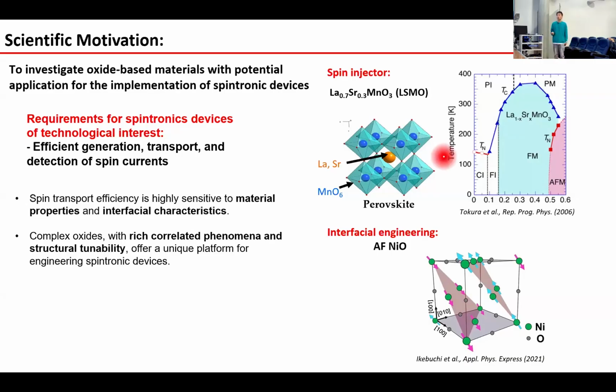In our case, we utilize the oxide LSMO, lanthanum strontium manganese oxide, as a spin injector. It's a very famous oxide material, and it has a high saturation magnetization and a Curie temperature above room temperature. And also the magnetic phase can be tuned by the substitution level of strontium. And also it's very important to improve the spin current transport at the interface. So we adopt nickel oxide on top of the LSMO to achieve the interfacial engineering.